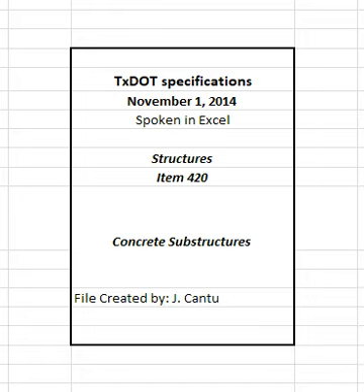Coat the joint surface with bonding mortar, grout, epoxy, or other material if a bonding agent is required as indicated on the plans. Provide Type 5 epoxy per DMS 6100, Epoxies and Adhesives, for bonding fresh concrete to hardened concrete. Place the bonding epoxy on a clean, dry surface, and place the fresh concrete while the epoxy is still tacky. Place bonding mortar or grout on a surface that is SSD, and place the concrete before the bonding mortar or grout dries. Place other bonding agents in accordance with the manufacturer's recommendations.